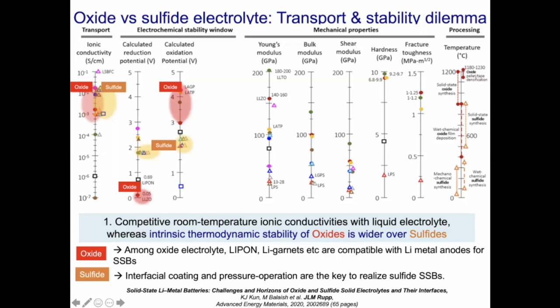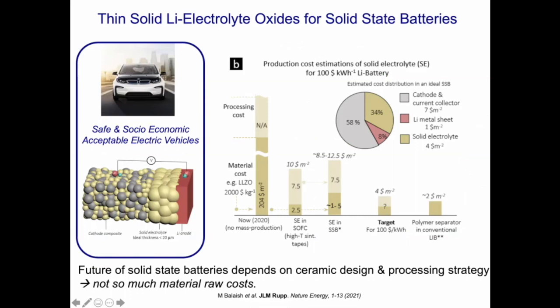So why I personally think that lithium oxide materials, in say garnets, are very interesting is that this is, I think, a great way to bring in pure lithium into batteries. However, what we also see, and that is what my talk will be about, is that we have to bring down the process temperatures from traditionally above 1000 degrees Celsius to much lower, as this significantly scales later with costs. And this is actually where the motivation goes for the next slide.